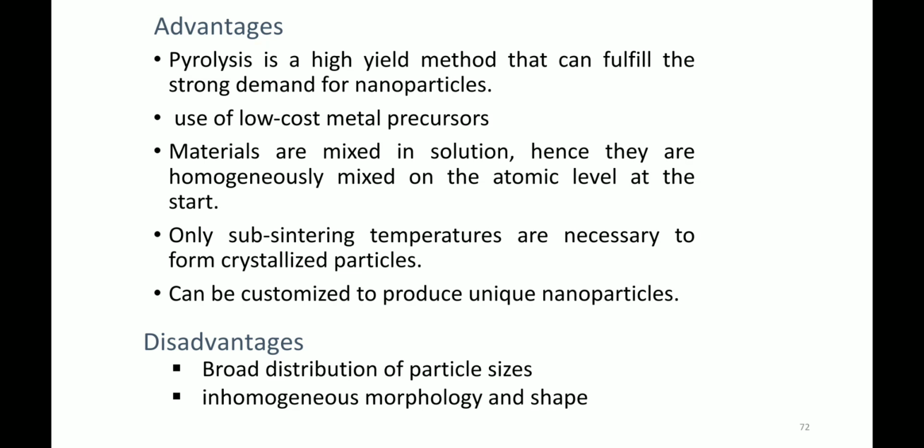It is not like there is a formation of zinc oxide and a formation of iron oxide. You have to optimize that by controlling parameters, but because the iron and zinc precursors are dissolved in the liquid, they have a homogeneous mixture at the atomic level. So this is a big advantage of this technique.